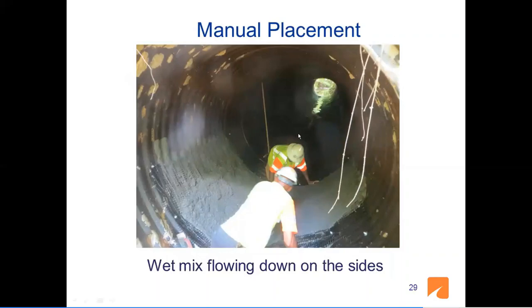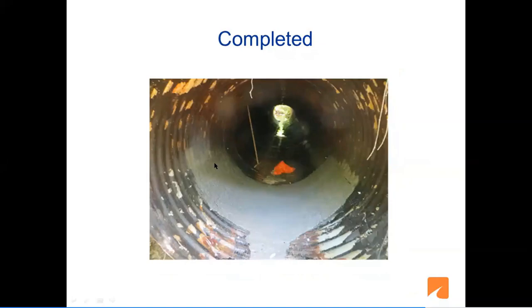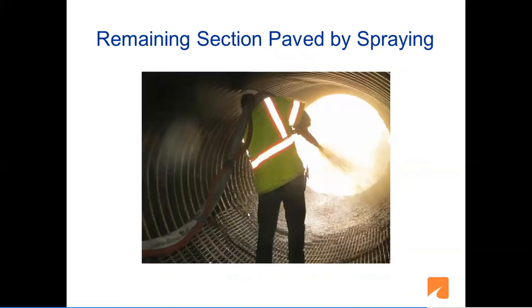like Dr. Mehran was talking about. And what we noticed is that along the sides here, it was sliding down, flowing down the sides, as you see here on this side. So what we did is waited about 15 minutes and then finished it up because it stiffened a little bit and we were able to push it back and complete the project. As you see, this is the completed section. And then we waited several months as the water flowed over this, and it was doing well. It was attached. Therefore, we decided to do the rest of the culvert.